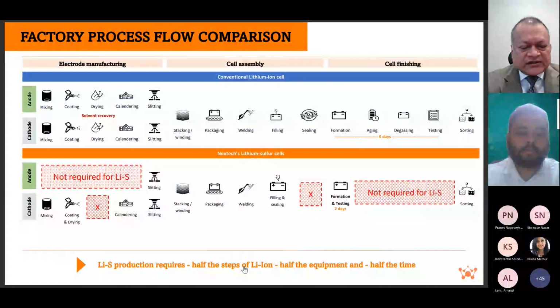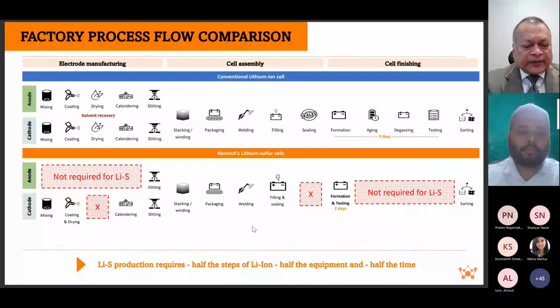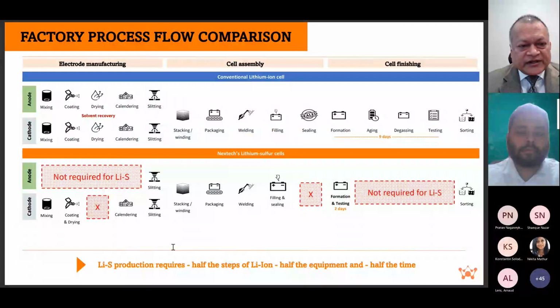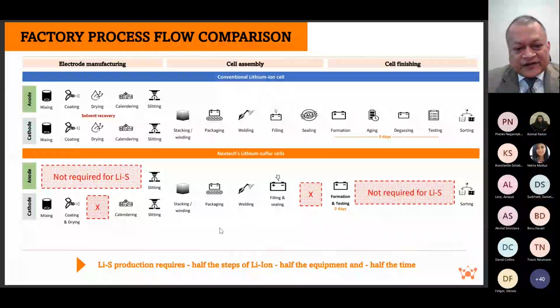electrostatically charge the substrate foil and apply the cathode active material, and then immediately anneal the material by rolling it through hot rollers. So this is something that we're thinking through that might reduce the cost of cathode line even more compared to where we are today. And obviously anode, no pasting, so no capex is required.